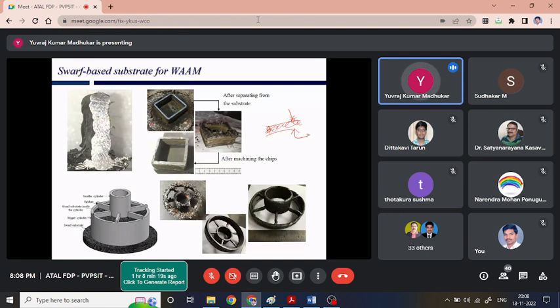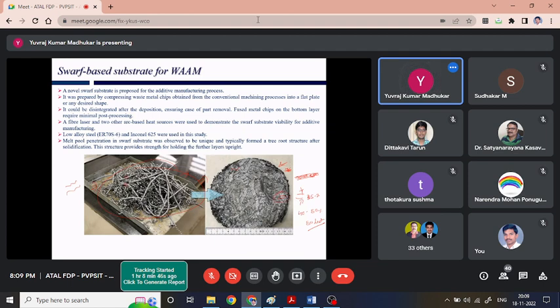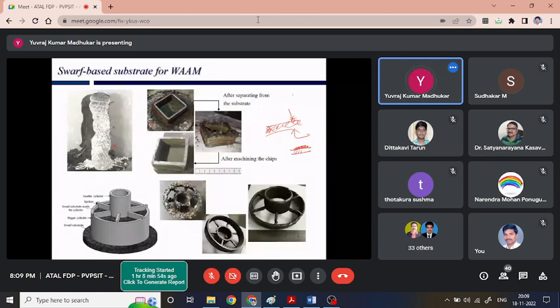Here we could see there is a metallic chip base on which we deposited this rectangular structure. Now the question comes, how is the fusion going to take place in this case? In the case of a solid base, there is a metallurgical bonding between the first layer of deposition and the base plate. What is happening in the case of a chip based substrate, or the swarf based substrate? Since we have this swarf substrate, if we look inside of it, it is nothing but a porous structure which has a lot of holes on it.